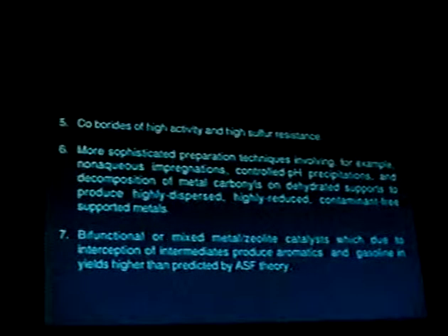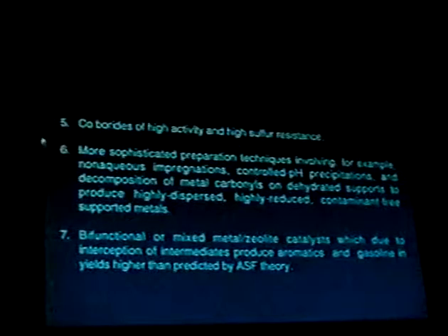High activity, olefin selective iron oxycarbide catalysts. Cobalt borides of high activity and high sulfur resistance. More sophisticated preparation techniques involving non-aqueous solvents or the decomposition of metal carbonyls to produce highly dispersed, highly reduced, contaminant-free supported metals. Bifunctional or mixed metal zeolite catalysts, which due to interception of intermediates produce aromatics and gasoline in higher yields than by Anderson-Schulz-Flory theory.